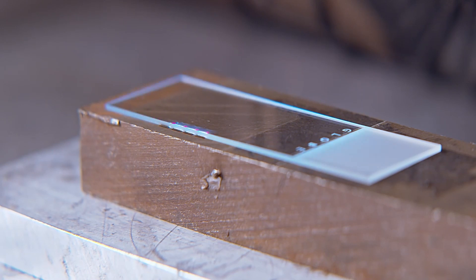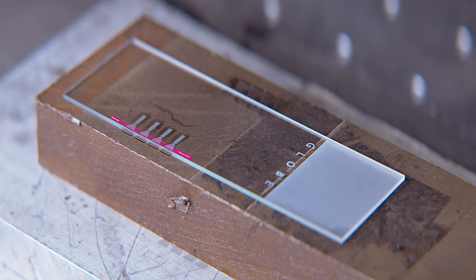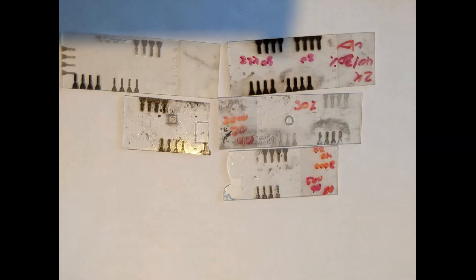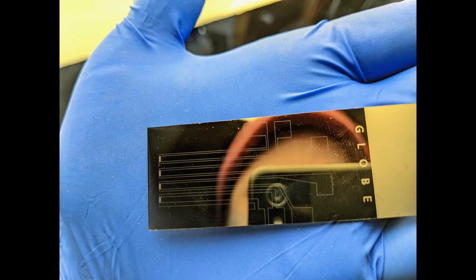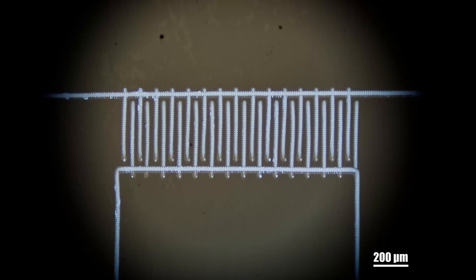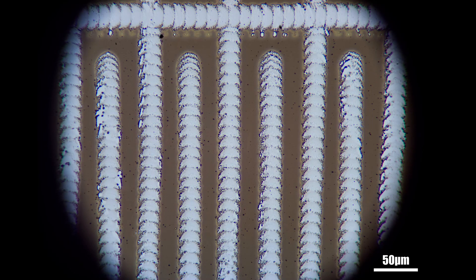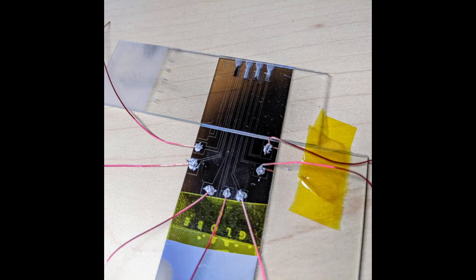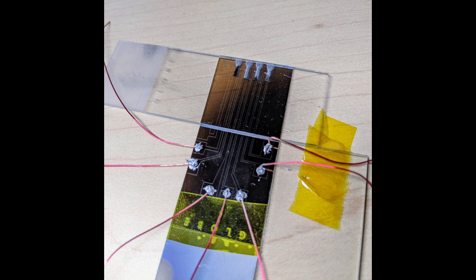The cavity was created using laser induced backside etching - it's similar to the wet etching I showed in a different video. You're ablating a piece of metal and the plasma explosion from that metal etches a little bit of the glass and generates a cavity for you. At some point I got my sputter coating machine, so I was able to lay down a thin film and then ablate away patterns on the thin film, which was a little more elegant than the copper tape I was using previously. Still haven't gotten this to work. It'd be kind of cool to get it to work someday, so I don't know, might revisit this one.